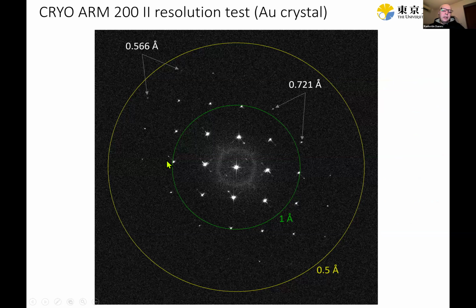Now, to test the machine initially, we used an oriented single crystal gold sample. Took some images, and here you see the Fourier transform of one of the best images. It shows spots along the tilt axis. So the tilt axis is something like this. I don't have it marked here because I don't know exactly where the tilt axis is. So along the tilt axis, we see spots up to 0.566 angstrom resolution, and perpendicular to the tilt axis, they go up to 0.7. So in all directions, the resolution goes beyond 1 angstrom, which is very satisfactory for cryo-EM applications where we don't usually reach close to 1 angstrom.